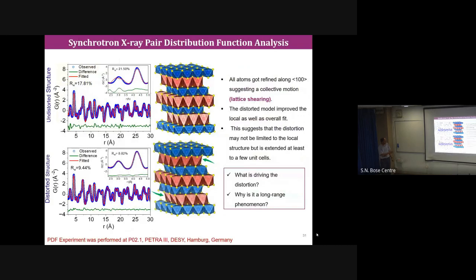And this is the synchrotron XPDF data, and the red lines are the fitting. So this is thallium bismuth sulfide. The structure was known for a long time, as I said, thallium octahedra and bismuth octahedra along the c direction. So with the single crystal data, we use the same structure file and try to fit the PDF data. You see, the first peak is not explained by the global structure. So then you have to give some distortion to fit this peak, and you get the layers distorted like that. The layers are basically having a pseudo shear with the thallium layer.